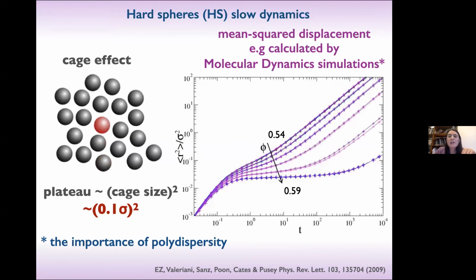Now, in computer simulations, sometimes it is much easier to look at the mean-square displacement of a given particle as a function of time. I report here the results of molecular dynamics simulations of hard spheres that we performed some years ago, just as a representative to show you that the same feature that happens in the density correlator, the plateau emerging, also happens in the mean-square displacement. Here I report results for hard-sphere simulations at packing fractions from 54 to 59. What happens is that this plateau, originating from the cage effect, becomes longer and longer.